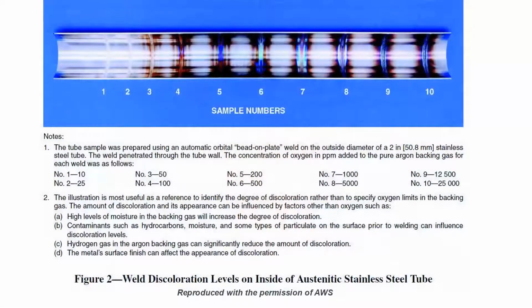When welding a tube or pipe, weld discoloration on the exterior is accessible and easy to remove. However, the interior of the tube is not accessible and large volumes of inert welding gas are required to displace the air. Effectively displacing air can be a challenge, but it is necessary to maintain corrosion resistance in the weld zone. The American Welding Society has produced a visual guide identified as D18.2,